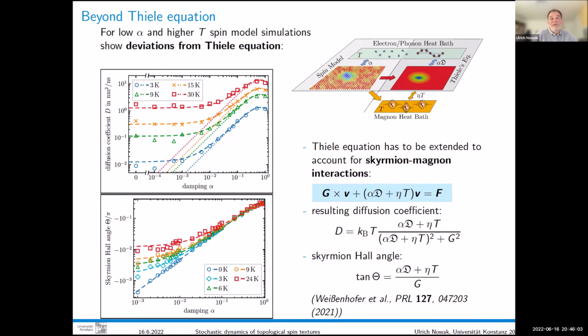So the rest of the film would be long-range ordered, but not in the ground state. We are at finite temperatures. So we have interactions of this skyrmion also with the magnons. And they are not described as a heat bath in the Landau-Lifshitz equation because you really simulate or you describe the magnons in the spin model. And in the Thiele equation, that is kind of neglected. So the magnon heat bath goes to a constant value of the background. So this part of the noise, you could say, is averaged out.